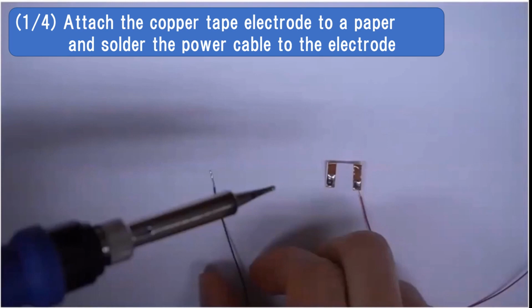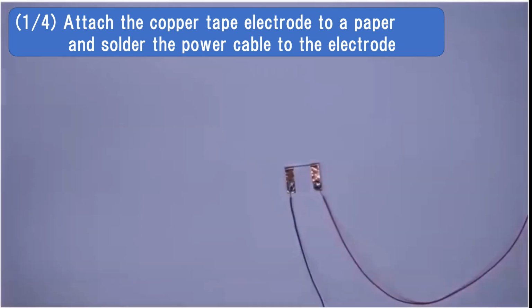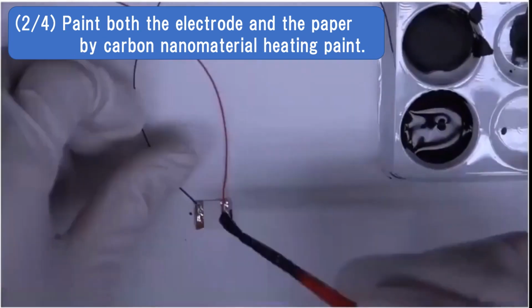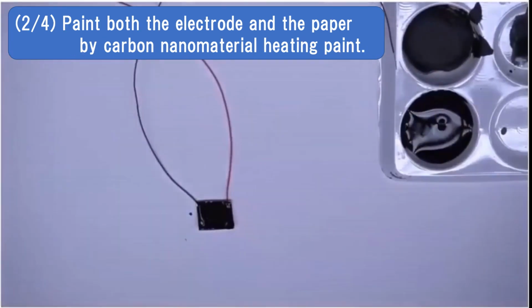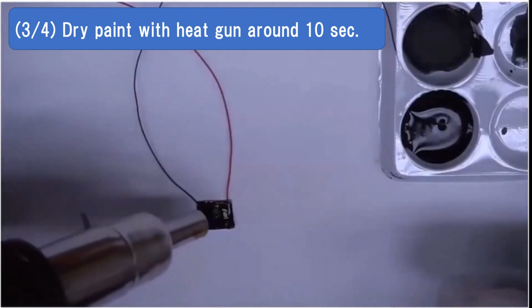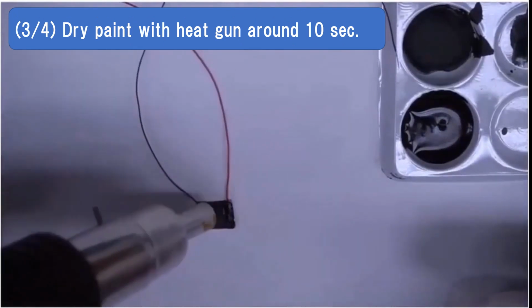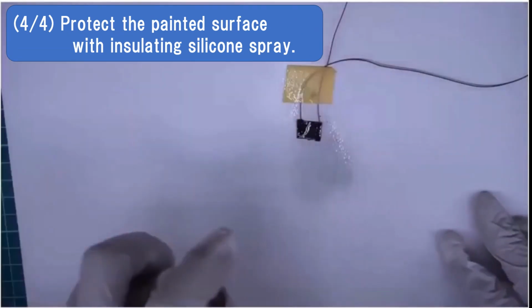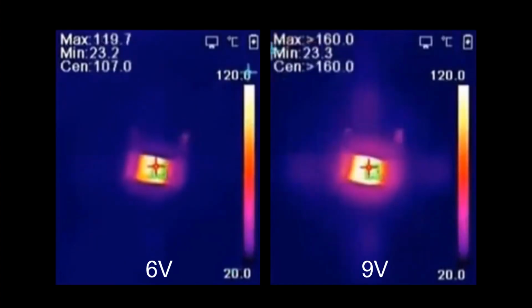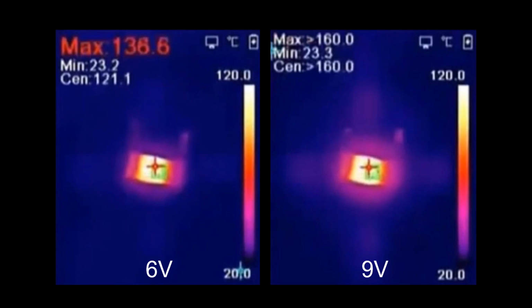The fabrication of the heater is very simple. In the following example, we used conductive copper tape as the electrode and 2 cm by 1 cm copy paper as a heating substrate. First, attach the copper tape electrode and power cable to the side of the paper. Then brush both electrode and paper evenly with heating paint. Dry the paint with a heat gun for around 10 seconds. Finally, to protect the painted surface from damage, apply insulating silicone spray. By applying voltage, you can see the painted area rapidly heat up in a few seconds.